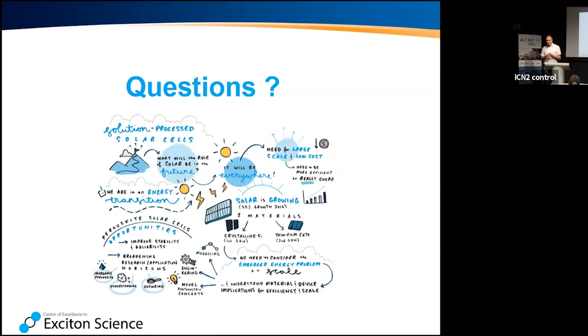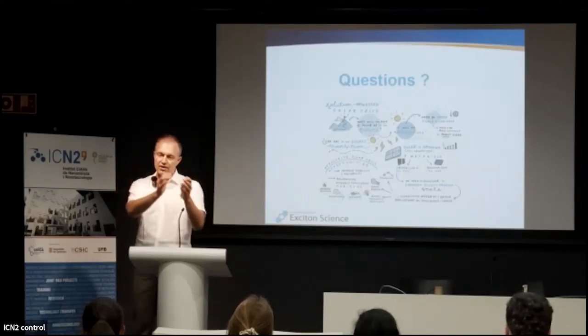A polaron is a charge carrier plus the strain that it causes around it. At high intensities, you still have your carriers, and each of the carriers still has its strain. I need to be careful what I'm saying. When you have a lot of carriers, they can move around, as you said. It's more a question of how many there are. You still have your polarons, but because of such a high intensity you don't have your gradients anymore, where there's a polaron here and none there, because they're just all over your material. You're pretty much saturating your material with polarons, so you can't have polaron-free areas in one place and not others.